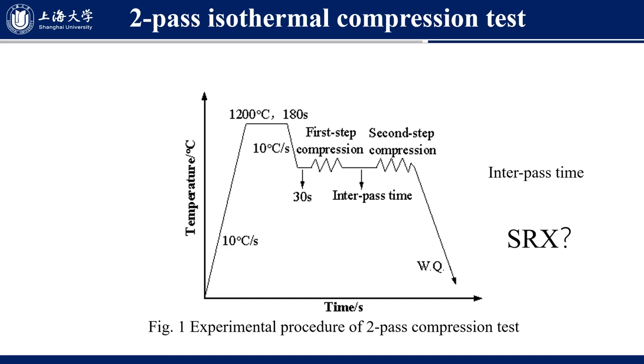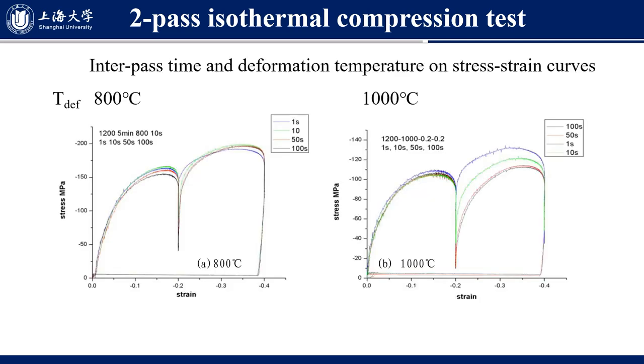We are focusing on the interpass time. What happened? Is there any static recrystallization? The effects of interpass time and deformation temperature on the stress-strain curves are shown in this slide. We can see at 800 degrees C, the curves are here. With different interpass times, the curves do not change a lot. At 1000 degrees C, we can see the second pass shows totally different flow stress behavior.